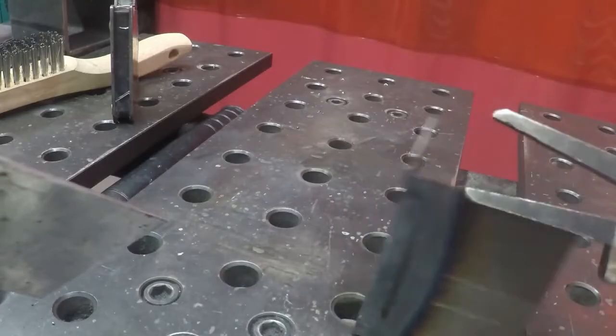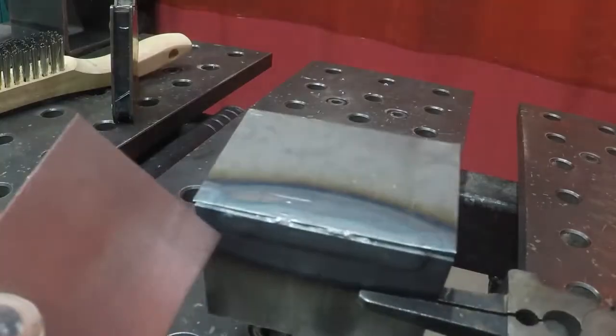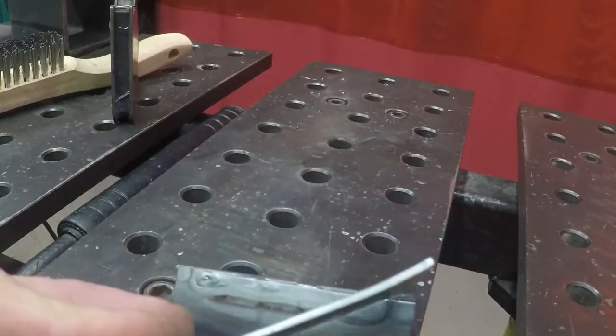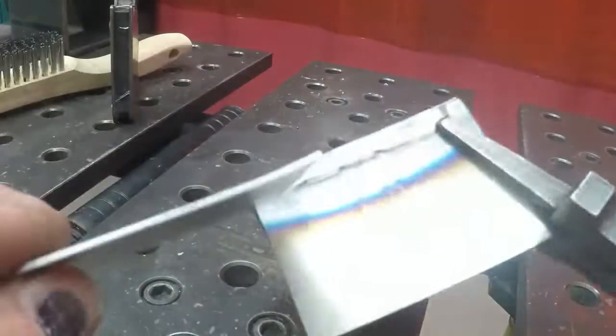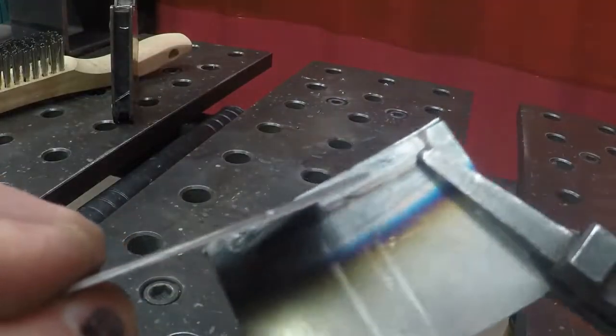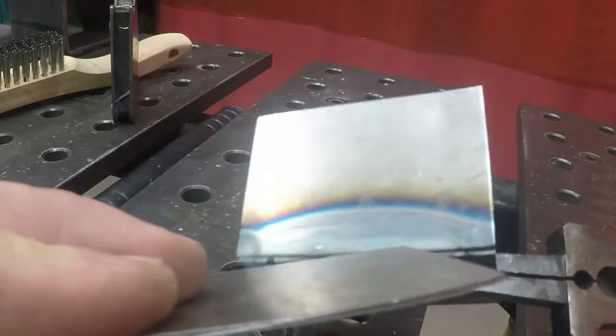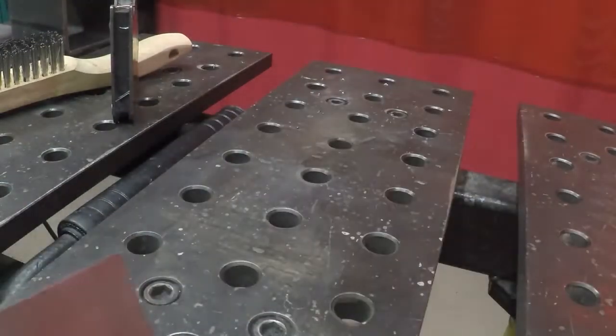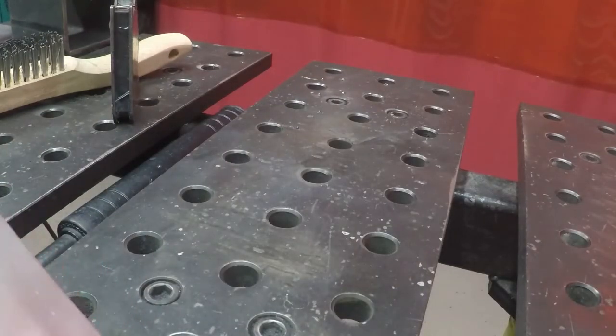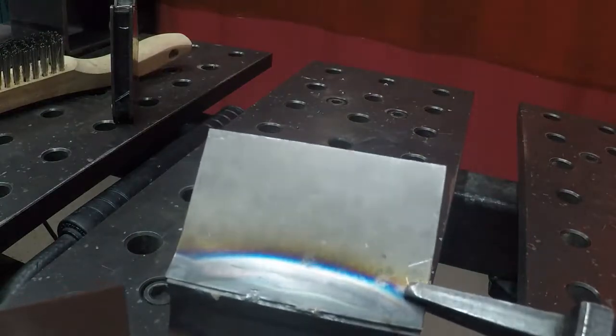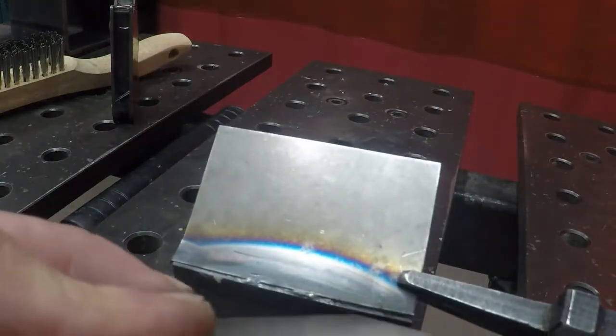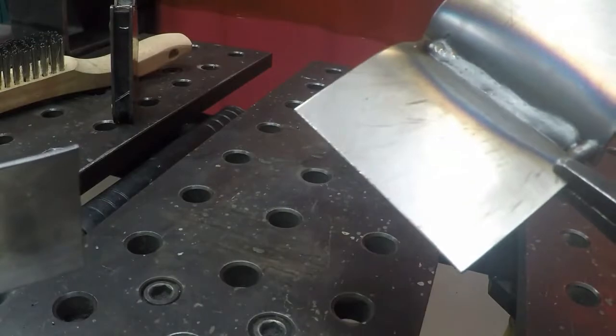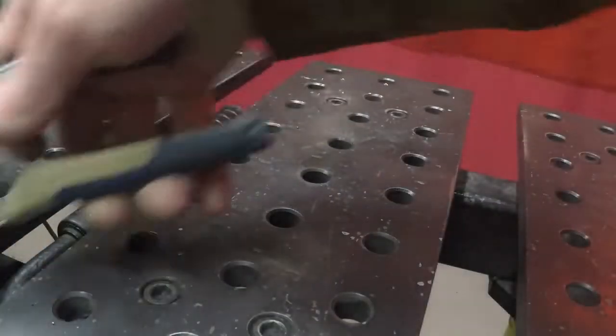And if we look at the back, we can see that I have evidence of penetration right through the corner. It looks like most of my heat is going on the top. Here's the heat affected zone, a little bit more than I have on the bottom. Let's give it the stomp test, and I look to see if I got anywhere where the weld peels apart. And you can see on this one, I don't have any peel apart on it. So that's a pretty good weld. We'll leave it at that.